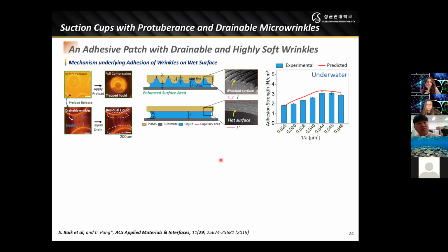Such adhesive performances can be explained by two mechanisms. The first one is drainage of water molecules, and the other is enhanced capillary interactions of the wrinkles. First, during attachment, most of the water is pushed out of the patch interface or into the chambers of the microcavities. After release of the preload, water residue remains trapped inside the microscale grooves of the drainable wrinkles due to strong capillary interactions. Therefore, sealing by the wrinkles also sustains the suction effect.